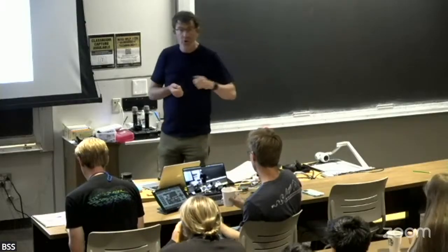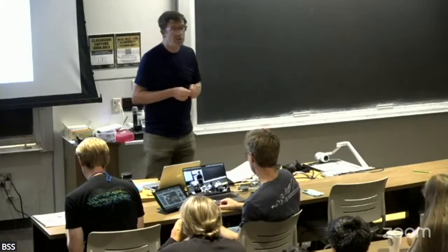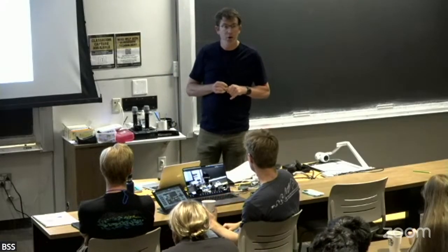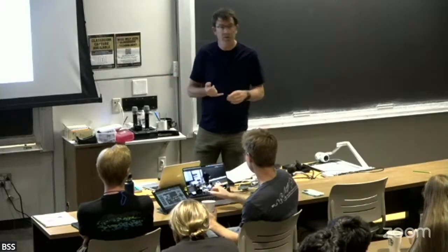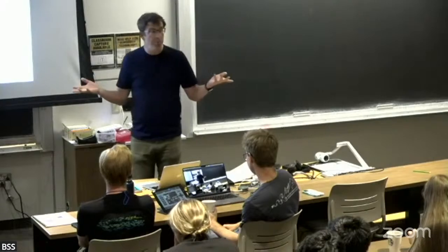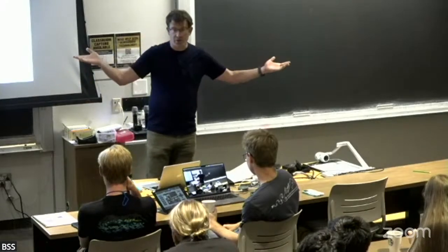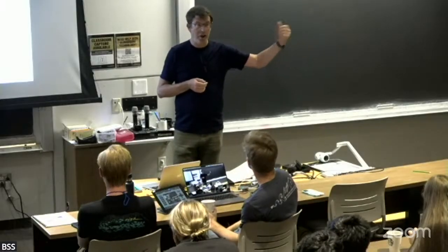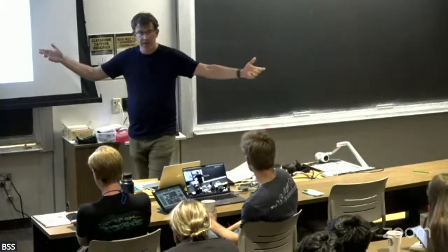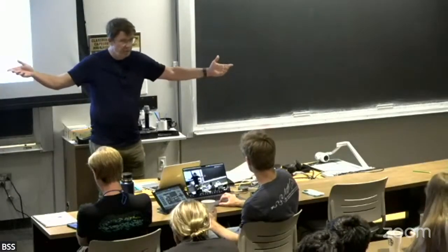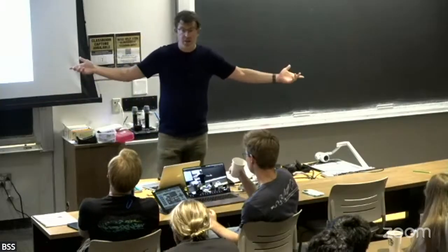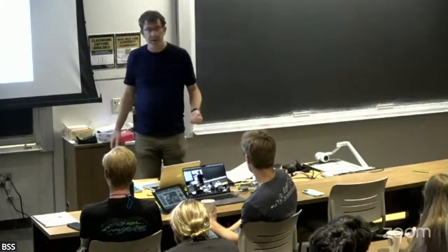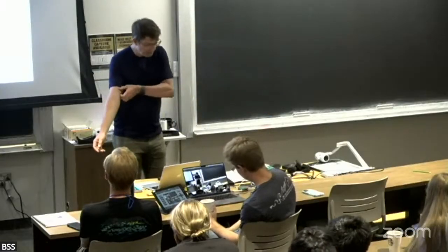I talked about, from those considerations, Kramers-Kronig transformations, which is the bread and butter of what we do in optical spectroscopies. Very often we'll measure one of the components of the complex response, but we need to know both. We want to know the complex conductivity, and so we'll use these Kramers-Kronig transformations. If we know all frequencies, or at least a broad range, we can use that to find the other response at any frequency. One of the things that comes out of Kramers-Kronig is sum rules, right? And we use sum rules all of the time in optics to understand things in a reasonably model-independent fashion.